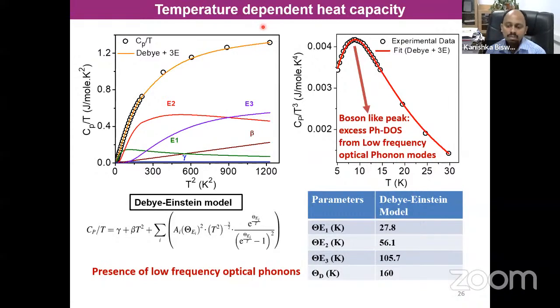So what are those Einstein modes? These Einstein modes are basically the low energy phonon modes, which are generated actually near this cadmium doping in this sample. And this low energy phonon mode tells that it has a high density of low energy optical phonons, which are also good to scatter acoustic phonons. You can see these low energy optical phonons are in the range of 27 to 105 Kelvin, and in energy it's only a few inverse centimeters. And the Debye temperature we have estimated is only 160 Kelvin, at which all phonon modes are excited. So this is actually a very low thermal conductive material. And then when we plotted Cp by T cubed versus T, we see a boson-like peak, which exactly tells that there are excess low energy optical phonon modes in this compound.